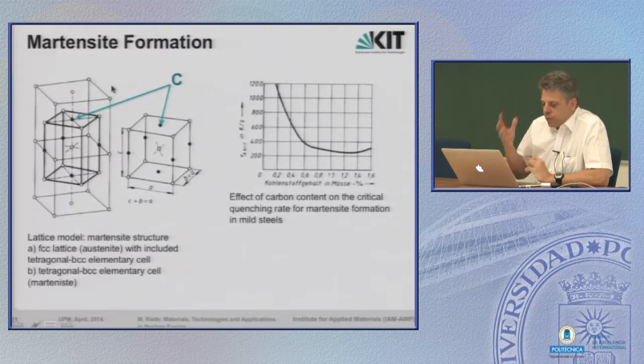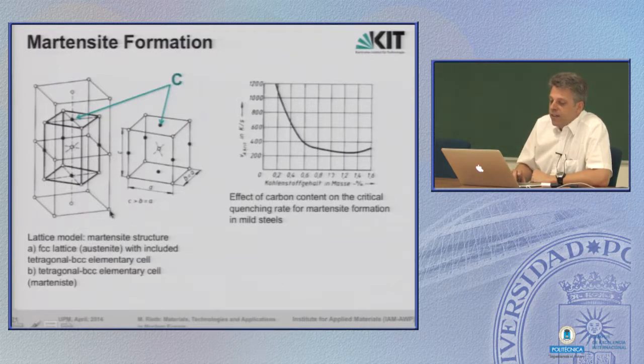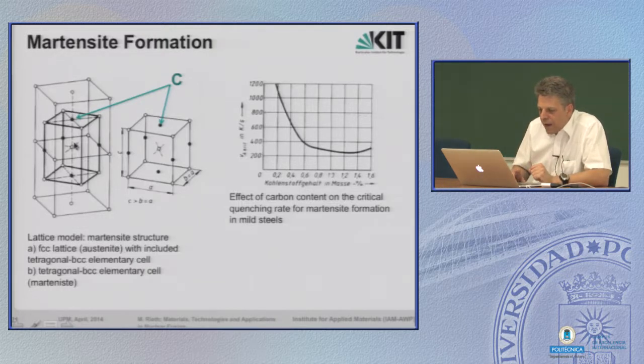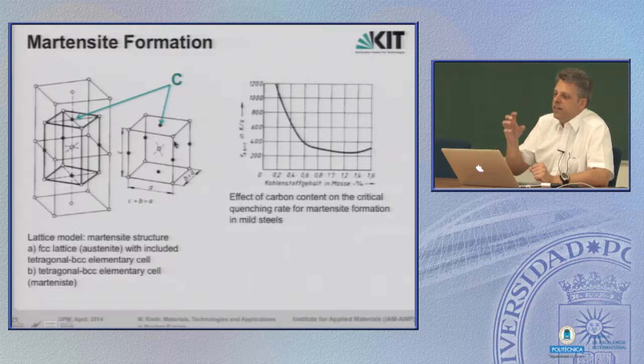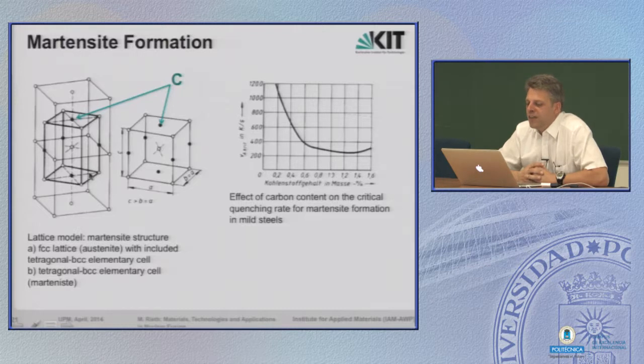Maybe if you can imagine in three-dimension lattices, somebody tried to show it here. The white dots, these are iron atoms. Here in the FCC lattice, that's a face-centered lattice, you see it here, four on the corners, one in the middle of the face. But we have a mix of iron and carbon atoms. So the black ones, that's the carbon atoms, they are located on interstitial sites. And the preferred sites for carbon are indicated here. And as a mix of both, you see here the black outlined structure within the FCC structure, and this can be already considered as sort of a tetragonal BCC structure.